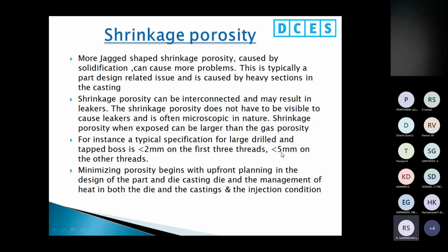So more jagged shaped shrinkage porosity is caused by solidification. During the solidification it can cause more problems. This is typically a part design related issue and is caused by heavy sections in the casting. So whenever you have big heavy sections, you have to be cautious about this kind of porosity. Then we can speak with the customer to modify the product design.